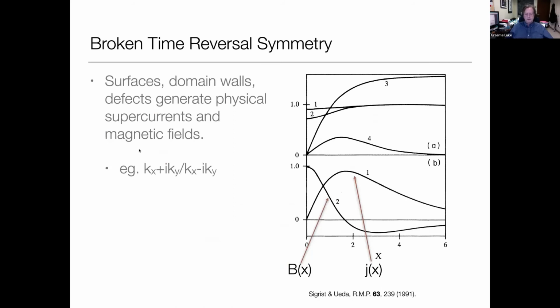One of the other symmetries we can look for is so-called broken time reversal symmetry. In the case of strontium ruthenate, which is a very famous example of this, we have a gap function which can be either a Kx plus iKy state or a Kx minus iKy state. And when you have boundaries, just like you have boundaries between different regions in a ferromagnet, where the order parameter direction, spins order, you'll have one domain where the spins are pointing in one direction, another domain they'll be in another direction. You have a domain wall between those.